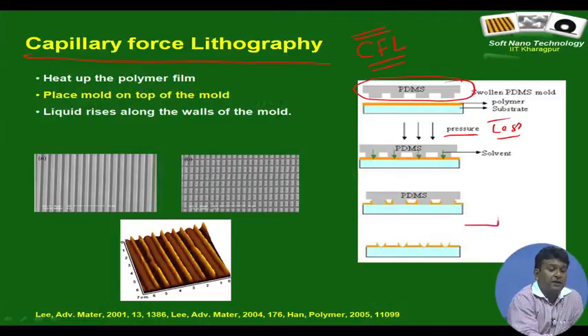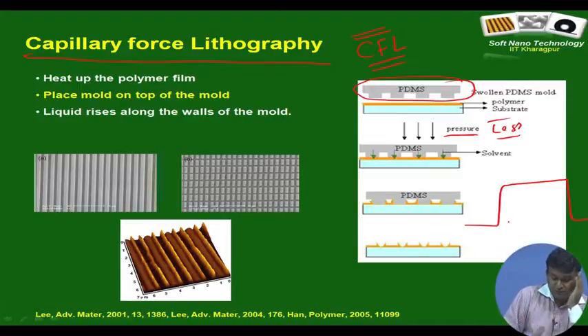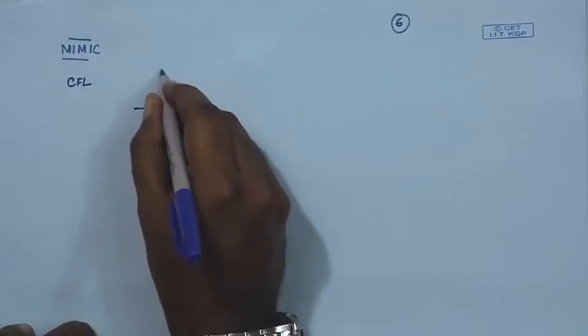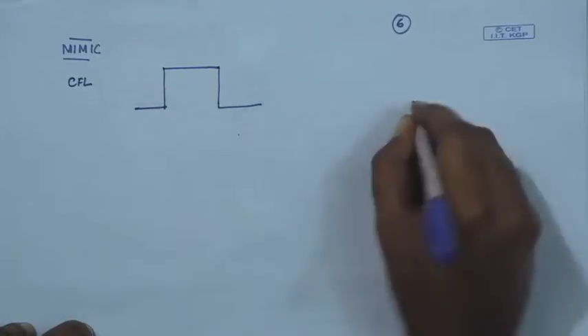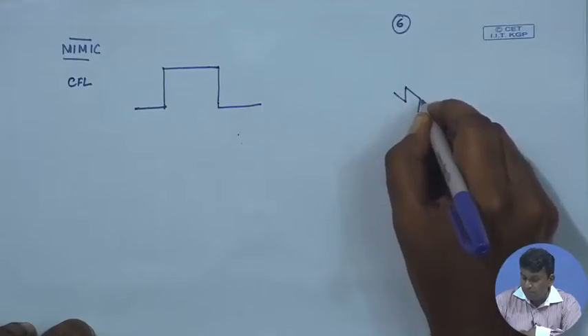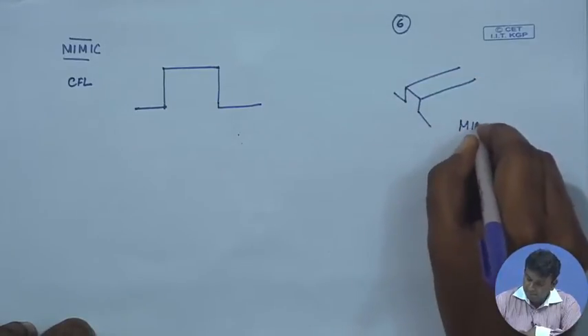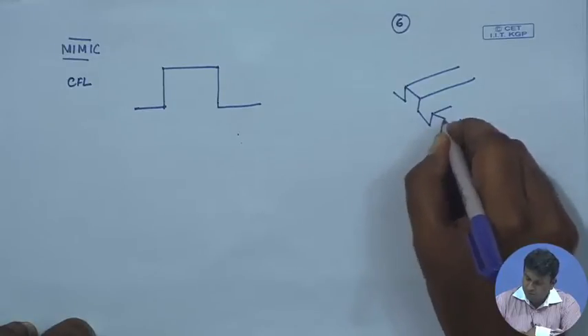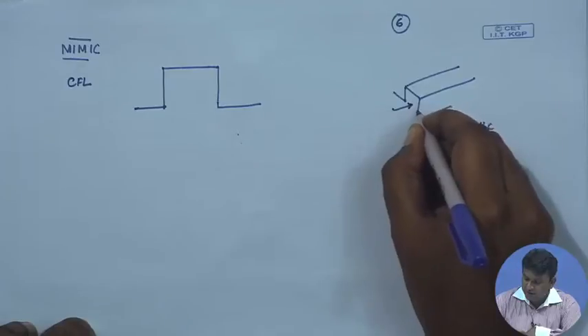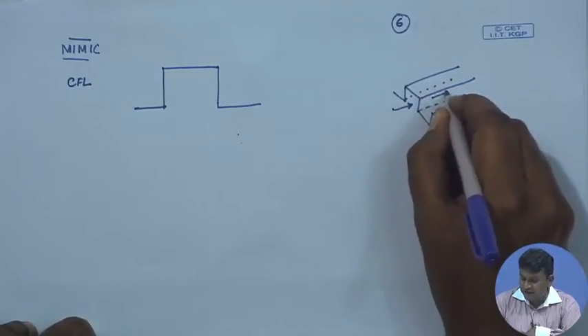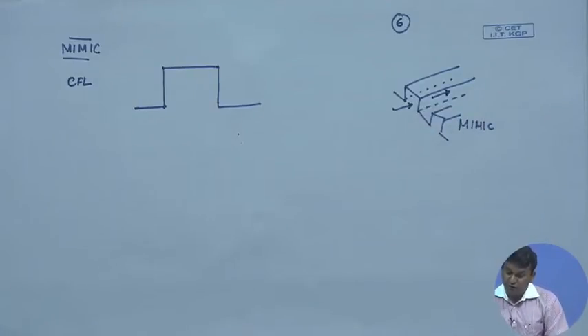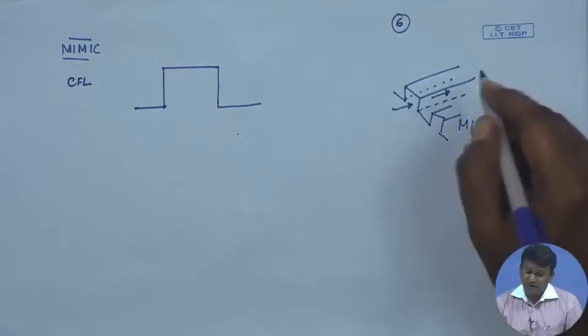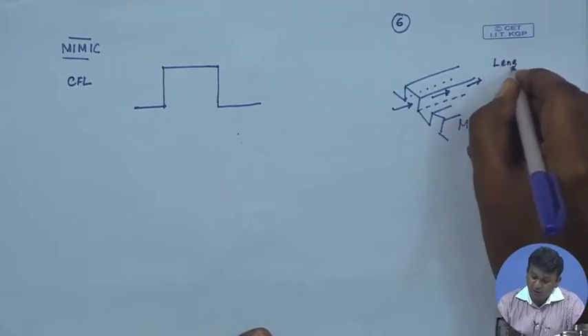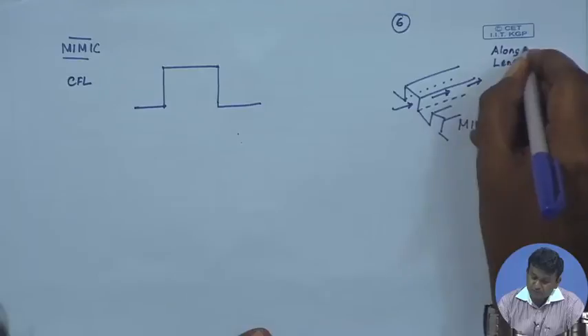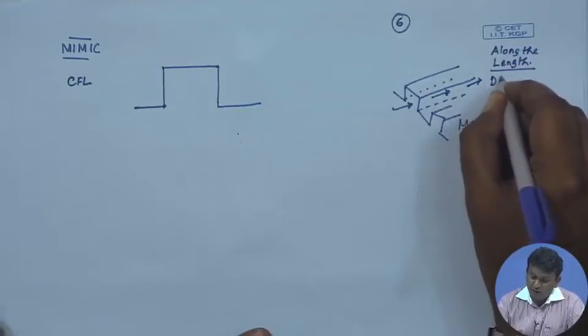In fact, the pattern replication in CFL is again by capillary dynamics, but unlike in MIMIC, sorry for the bad quality of drawing. So, this is the capillary driven dynamics in MIMIC. I am just showing one of the channels. It relies on the capillary driven flow along the length of each of the channels. So, firstly the mold filling is along the length, and a dilute solution.